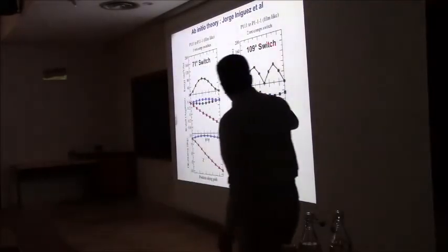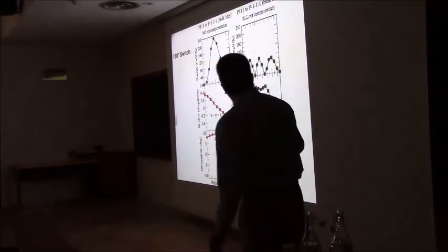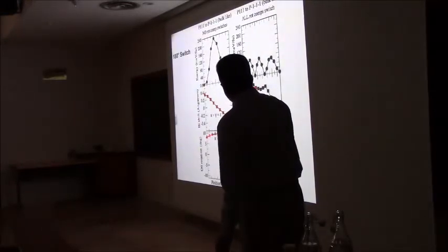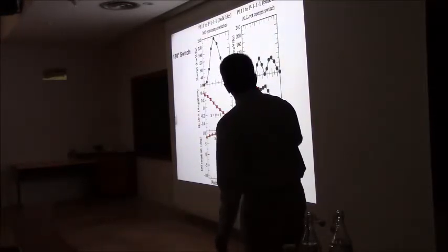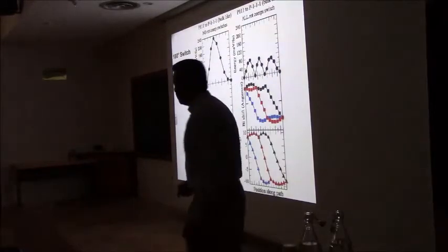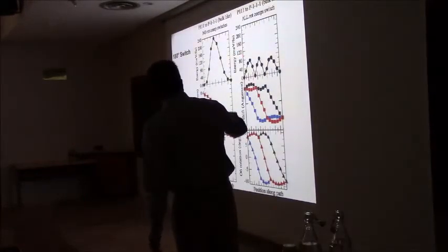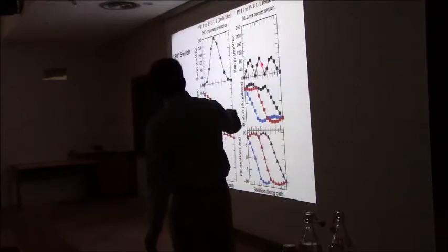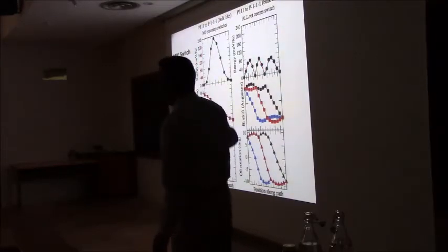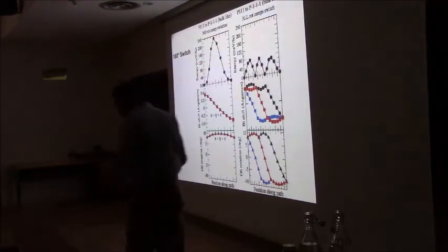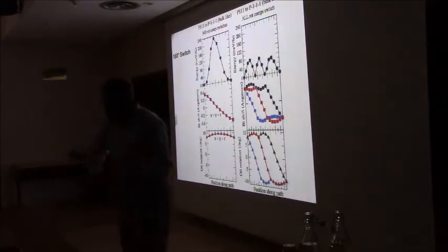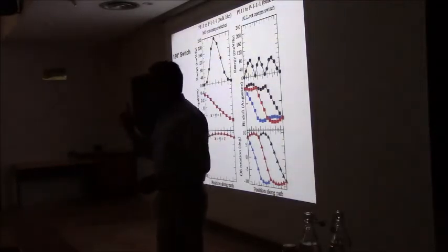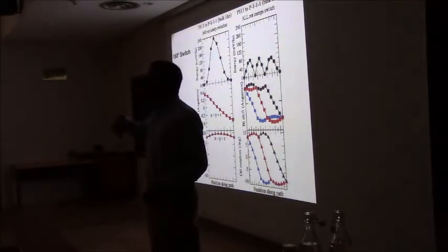You can go for the 109-degree switch. I'm going to finish up with the 180-degree switch. You can see X, Y, and Z, all of them are changing. And he found that doing this process was much easier than doing this. So the message there was that switching of the polarization by 180 can be accompanied by a 180-degree switch of the canted moment, depending on how it goes.